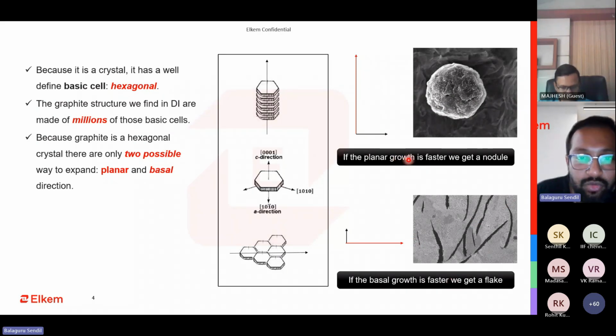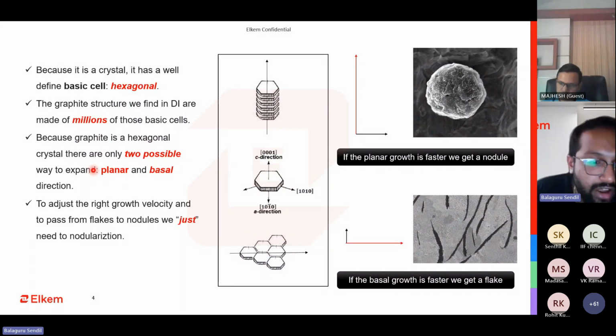So this is the logic in which the carbon, when it is getting stored or coming out as graphite, forms this hexagonal structure, and the way this hexagonal structure is growing determines whether it is a flake graphite or a nodular graphite. So what we have to do is just adjust the speed or the growth velocity, whether this axis is growing fast or this axis is growing fast. If you are able to control this speed or the growth velocity, you will be able to determine the shape of the graphite. It can be a flake or it can be a nodule.